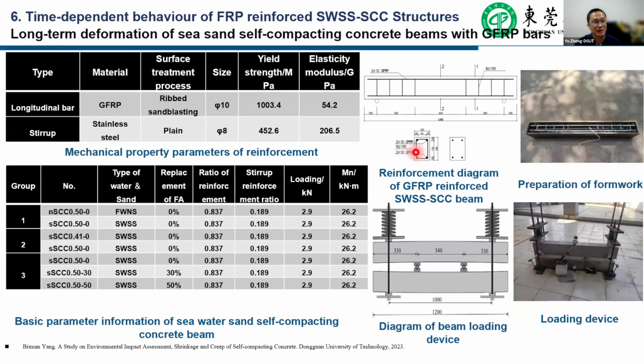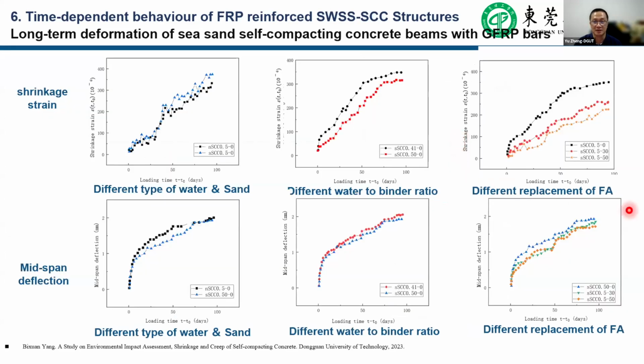And the final part of this study, we developed concrete beams reinforced with GFRP, constructed using seawater and sea sand self-compacting concrete. We try to investigate the long-term deformation. In total, due to the time limit, I will speed up my presentation. The long-term deformation of the test beams is still rapid, after the transfer period at 28 days.